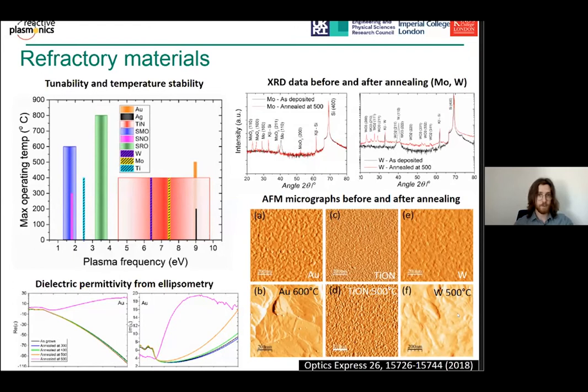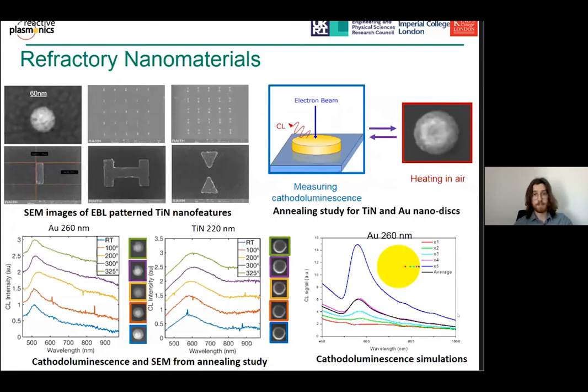But these were thin films, so we're also interested in nano-fabricated devices. So we developed for these alternative material platforms our in-house patterning capabilities. For example, titanium nitride is known to be mechanically robust and stable, so it cannot typically be patterned using existing patterning methods. So we had to develop a patterning method that would allow us to fabricate nano features. And we did this using electron beam lithography and reactive ion etching, a chlorine-based reactive ion etching process. And as you can see here, we can achieve films with minimum feature sizes of 60 nanometers diameter. And we can also deposit arrays of antennas of various shapes using titanium nitride.